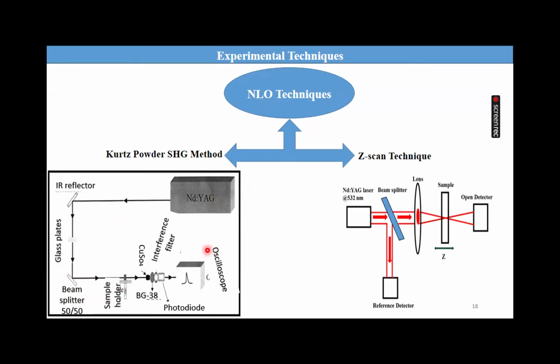There are two ways to use this laser. The laser produces single 8 nanosecond pulses while operating in a single shot mode. The laser generates a continuous train of 8 nanosecond pulses at a repetition rate of 10 Hz while operating in the multi-shot mode. A single shot mode of 8 nanosecond laser pulses with a beam spot of 1 millimeter has been used in the current work. A mirror and a 50/50 beam splitter are used in this experimental setup to produce a beam with a pulse energy of approximately 6 millijoule.